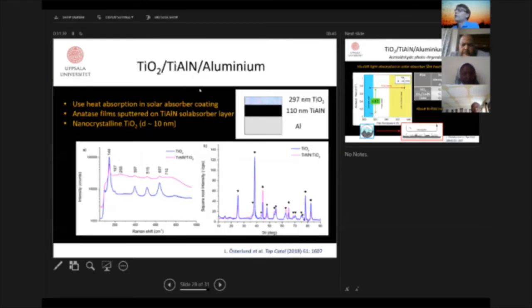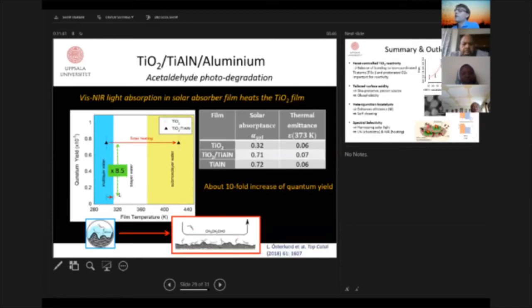Then going to a solar absorber, say for a water cleaning system, you place here a perfect solar absorber which becomes really hot. Then you can improve the same reaction rate by easily a tenfold increase of the quantum yield. So this is clearly a possibility. And this shows the numbers for absorption coefficient and the emissivity of these coatings. And this shows how the film temperature is increasing upon solar heating. And it becomes really hot, and you actually improve the quantum yield by tenfold. This is a lot.